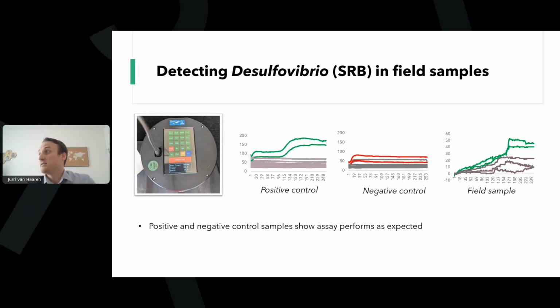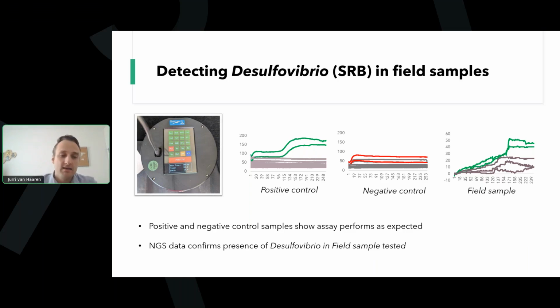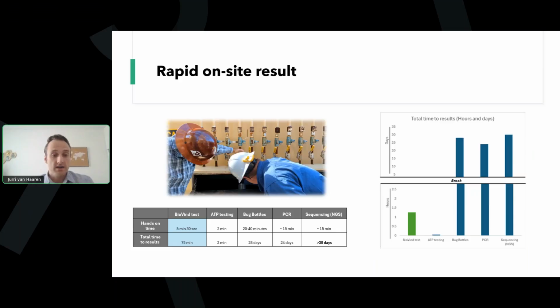We then wanted to validate that these results are accurate. So we took these exact same samples and did next-gen sequencing testing on them, and that testing confirmed that the 4 samples that showed up negative for us also showed up negative with NGS. And the sample that showed up positive for us was confirmed to have Desulfovibrio in it. Basically, our test can accurately detect microbial species when it's there and not detect it when it's not there. So that's great, the test works well on site.